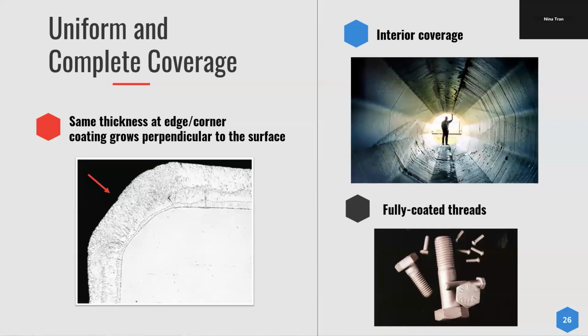All right. I mentioned it a couple times. You get uniform and complete coverage. Interior coverage of hollow structures. You also get the same thicknesses in edges and corners because the coating grows perpendicular to the surface. It is a chemical reaction, so it's growing the same everywhere, regardless if it's on a flat surface or edges or corners. And you also get fully coated threads as well, which are usually centrifuged or spun to remove all the excess zinc.